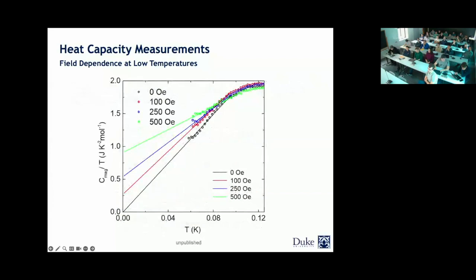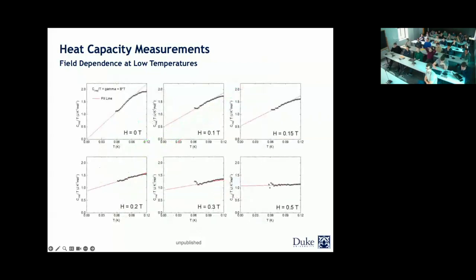But what we saw is that definitely when we start to go up in the field, the data starts to go up as well. Specifically, when you extrapolate that to low temperature, which would be the perfect scenario, it clearly shows that there is an upturn as a function of field. That was very good news for us, that at least in the second scenario, we were able to look at the different fields, and they also show what was predicted by the mean field theory from Patrick's paper.